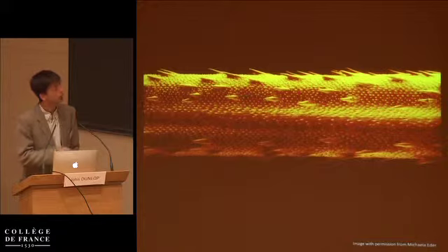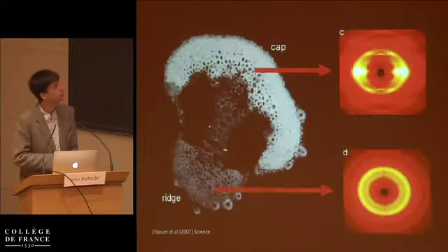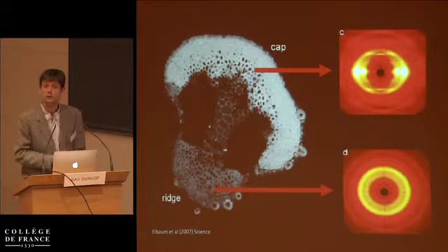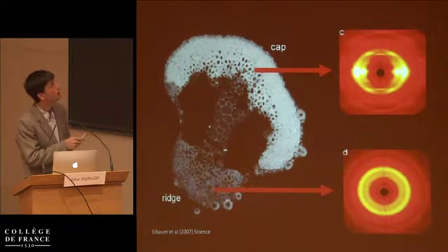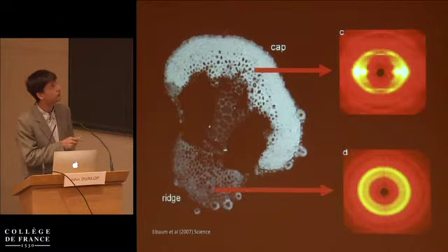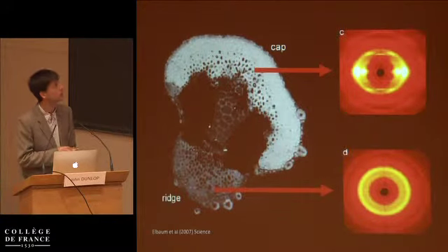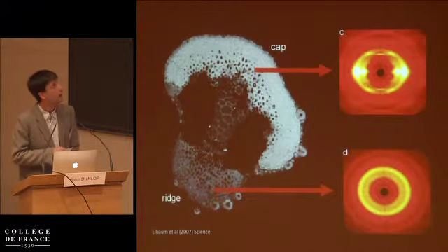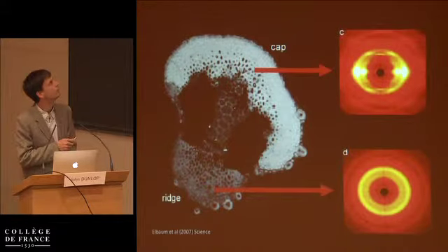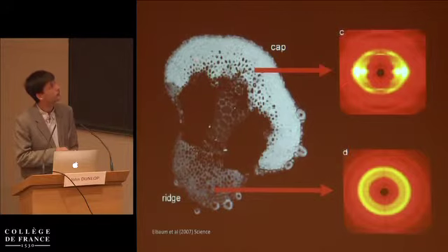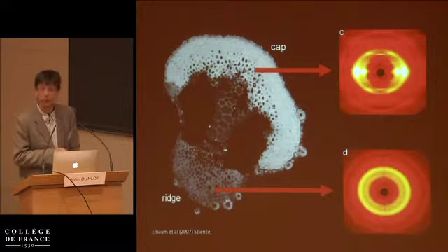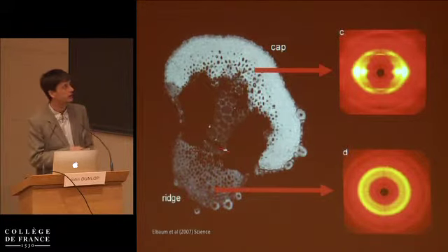And if you make a cut through the cross-section and look at this using scanning acoustic microscopy, which gives you an idea of the mechanical properties, you see that there is a region of high intensity, so high acoustic impedance, reflectivity, I think, and one region of low intensity. And by using small angle X-ray scattering and wide angle X-ray scattering, what they managed to observe is that there is a strong orientation of the cellulose microfibrils in this cap region, on one side of these awns, and a more random orientation in the other region.